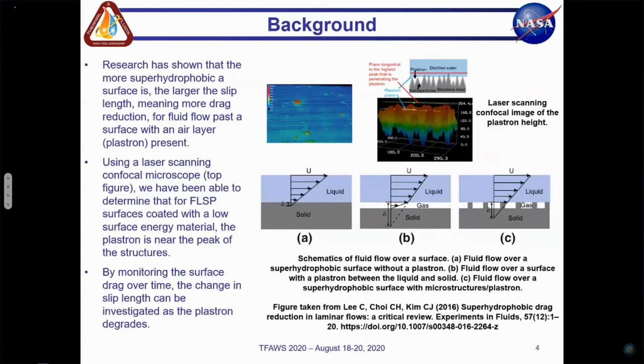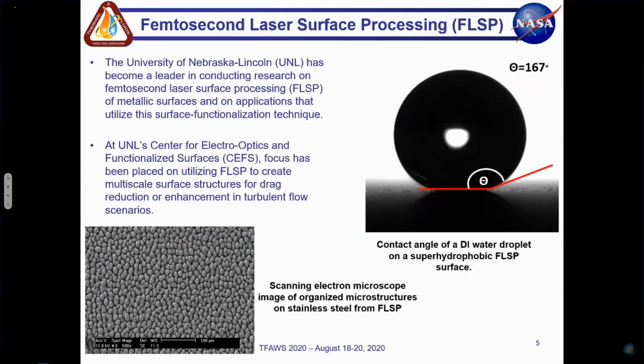But then you have C, which is typically how our surfaces start, where you have microstructures that trap this air or vapor layer in, and you're able to get a larger slip length, but not quite as much as having that uniform layer. But it's more stable over time, and you don't typically have to regenerate. Now, what we noticed with these surfaces is that we typically went from C, and then over time this plastron degrades and the air goes away. We moved to more of an A with the microstructures, where you have a fully wetted surface and you're still getting some slip.